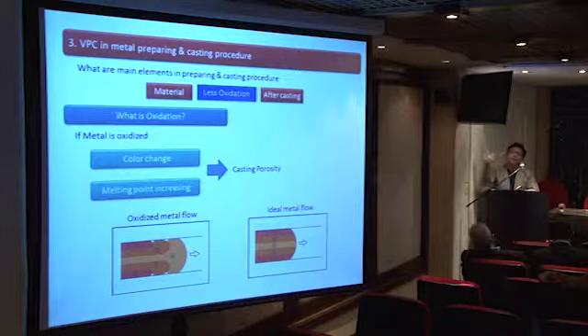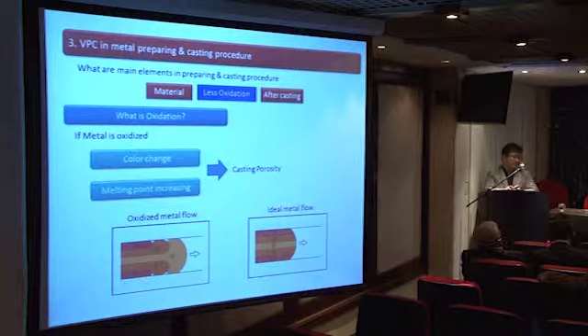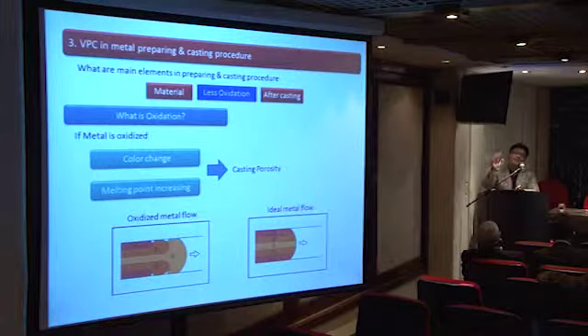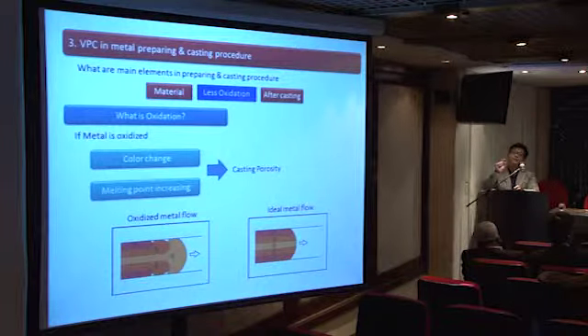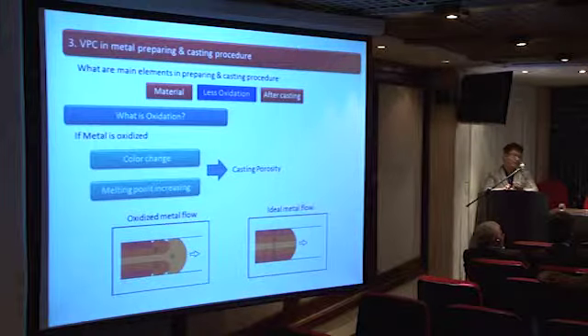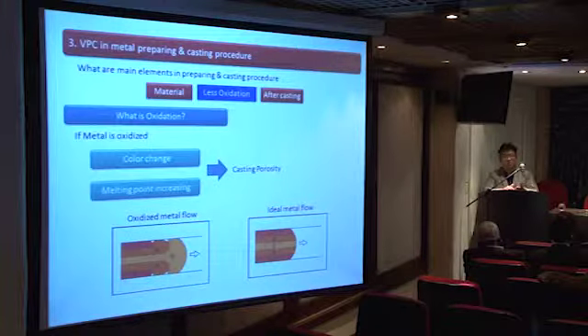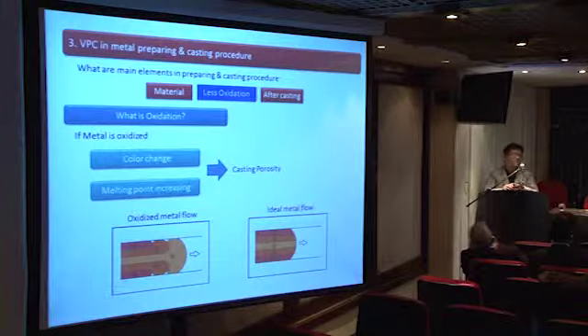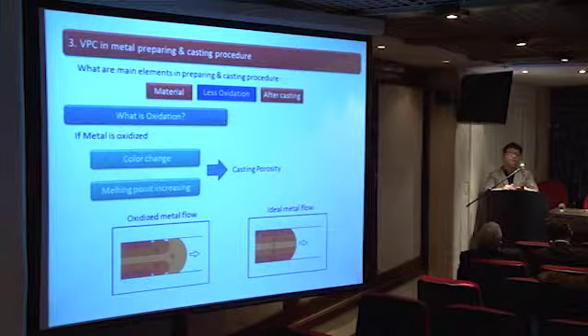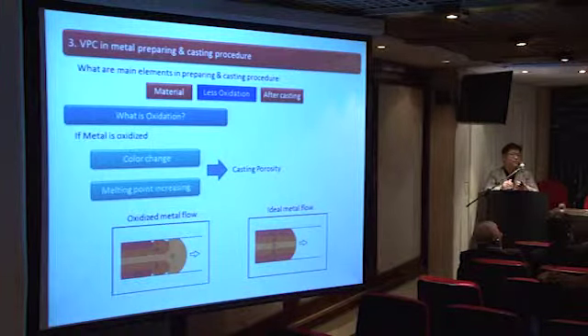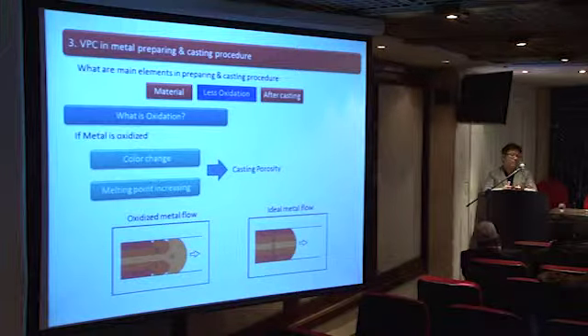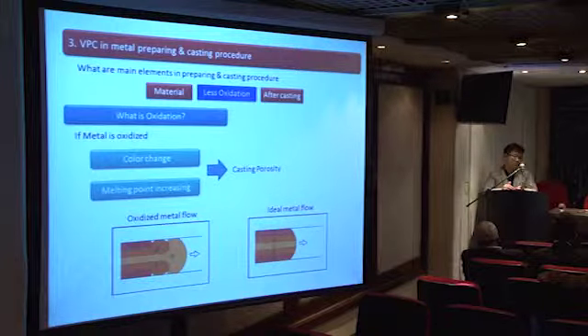If you see on the right, the same picture as in the burnout process, this is an ideal metal flow, where from number 1 to number 3 will be flowing at the same time. On the left-hand side, since the melting point changes and each metal has different densities, which is not mixed properly due to oxidation, the oxidated metal flows, as you see, number 1, 2, 3 in a completely different velocity. And where it attaches makes a turbulence against the metal, where you have the gas porosities.